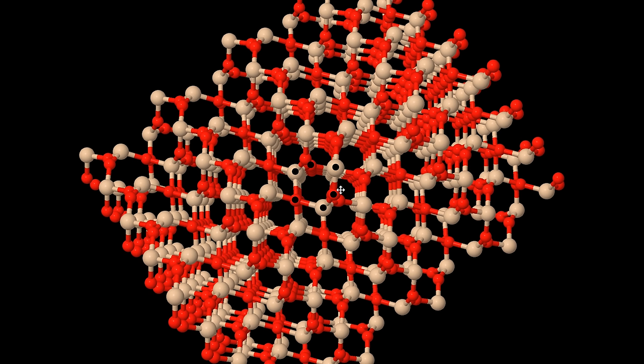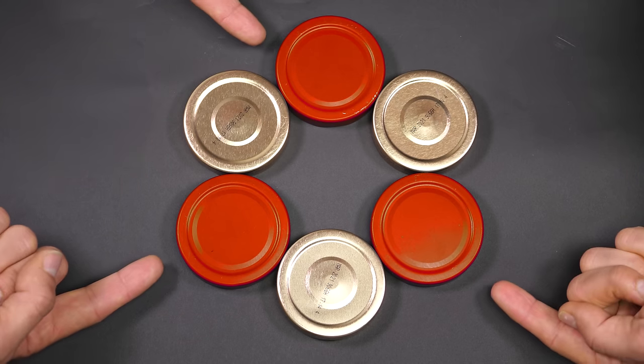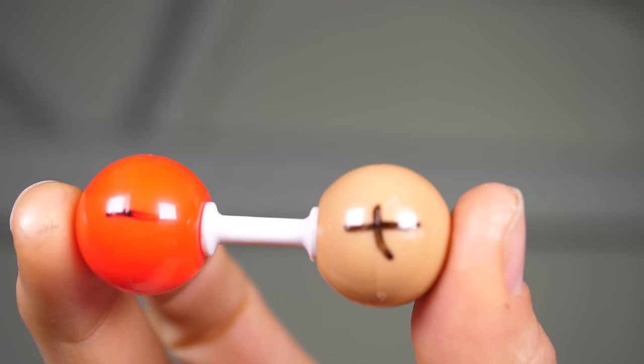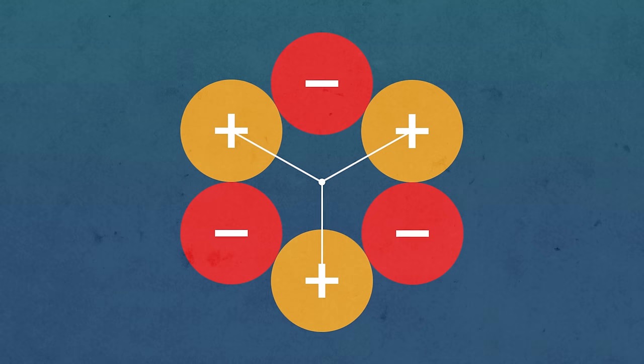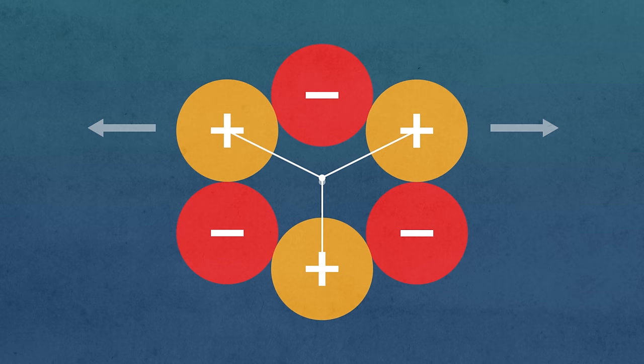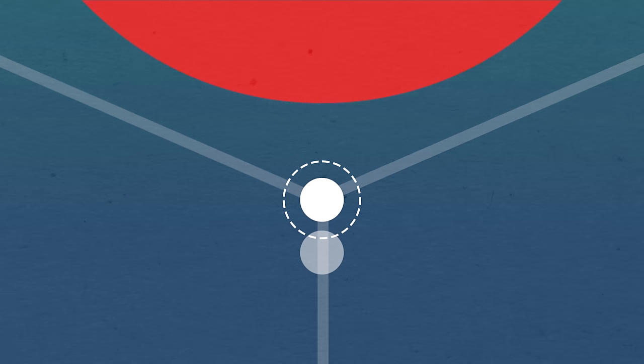It's actually a spiral going into the screen, but for simplicity we're going to think of it as a ring. These three crunchy peanut butter lids represent silicon atoms, and these three smooth peanut butter lids represent oxygen. So when you compress a crystal of quartz, you're squishing these hexagons. But crucially, the bond between oxygen and silicon isn't quite even — the oxygen is a bit more aggressive in the way it holds onto its electrons, so the oxygens are a little bit negatively charged and the silicons are a little bit positively charged. Think about where the average of all the positive charge is in this diagram — it's a bit like the center of mass, but it's the center of charge. It's there in the middle between these three silicon atoms. But watch what happens when you compress the crystal: the two side silicons move outwards but they don't move vertically, and the bottom silicon moves upwards. So the average position of these three positive charges moves upwards slightly.